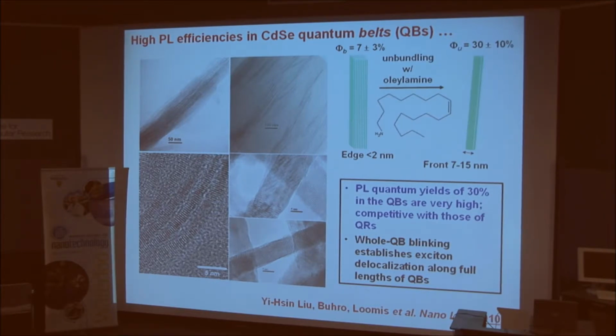So we were very surprised to find that the photoluminescence efficiencies in these belts can be as high as 40%. And who would expect that? Because after all, a belt has a larger surface area than a pseudo-cylindrical wire. If anything, the efficiencies should have been lower. We never expected this. So obviously with that, it occurred to me that belts can be wires too, right? That could potentially transport energy and charge over the long dimension. And these efficiencies are so high, it indicates that there's something good about these belts.